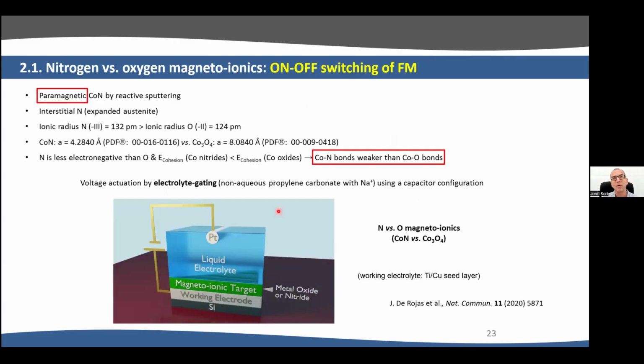Now, the problem of cobalt oxide is that it is very slow, as I have shown. So we thought maybe another material could be better. And we thought of cobalt nitride. Cobalt nitride is also cubic. Actually, the advantage of cobalt nitride is that the electronegativity difference between nitrogen and cobalt is lower than between oxygen and cobalt. So in other words, cobalt nitride bonds are weaker than cobalt oxide bonds. So we did the experiment.